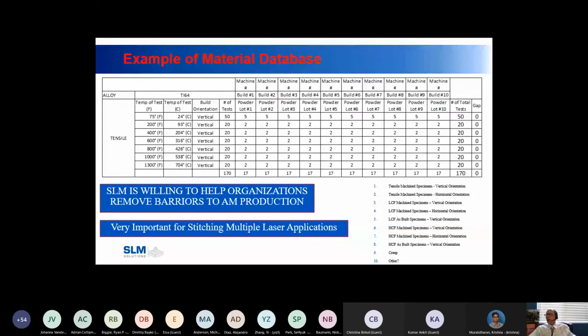Typically, to do an MMPDS, you have to buy 10 different powder lots. All right, so I set this up for Ti 6-4 material. You're going to test in these 10 lots 170 vertical specimens. As I said before, a room temperature test is roughly $110. So there's $5,000. And as you go up in temperature, you go up in price because there's a dwell time to get the part to 1300 degrees Fahrenheit. Typically, you're not going to go much hotter than that for titanium. You could, for nickel; this could go all the way up to 1900 degrees, depending on the alloy of the nickel. So you're going to do 170, then you're going to do 130 horizontals, and that'll give you your 300 tensile.